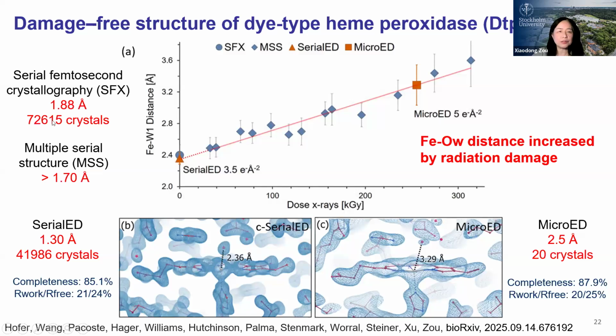For serial electron diffraction, we obtained 1.3 angstrom with 42,000 crystals, and compared with serial femtosecond crystallography using XFEL, the resolution is 1.88 angstrom with 72,000 crystals. And the XFEL data is normally regarded as damage-free. So this is the iron and the water distance, which is here.